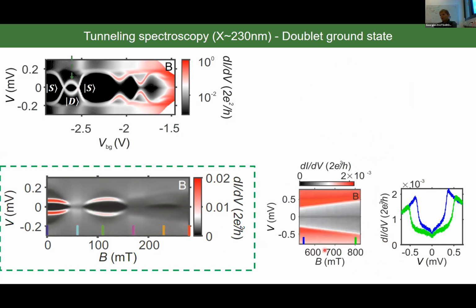If you go to much higher magnetic fields, where practically superconductivity is dead, if you sweep your magnetic field from 600 to 800, you can follow the evolution of the Kondo peak as it splits, and from there we can extract a g factor of about 10.